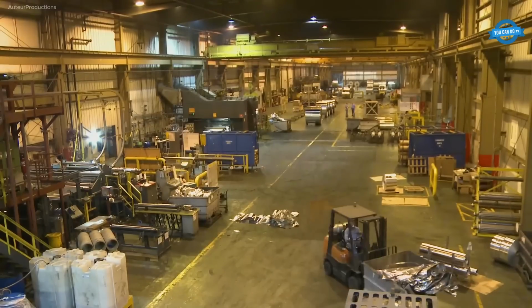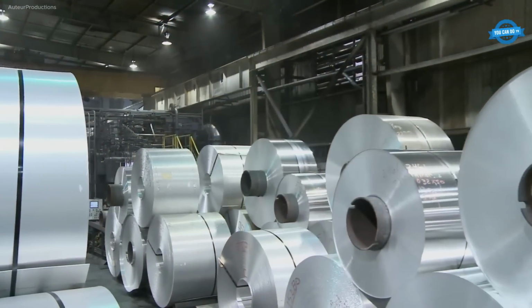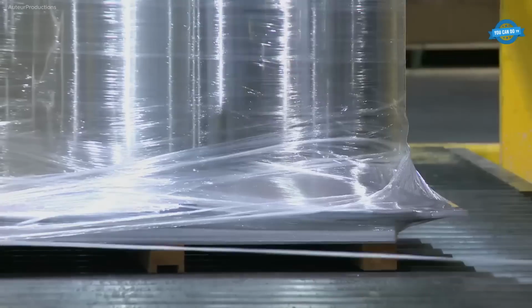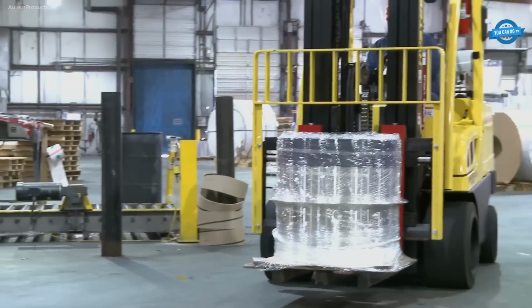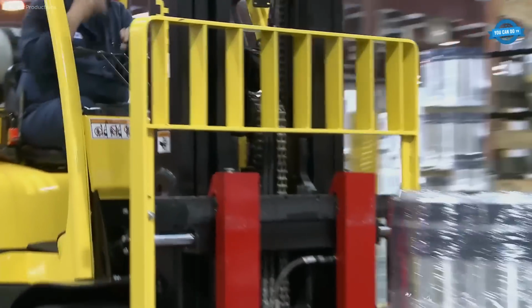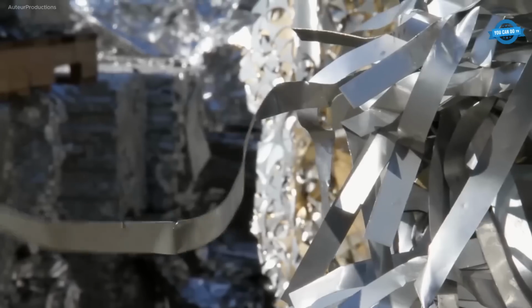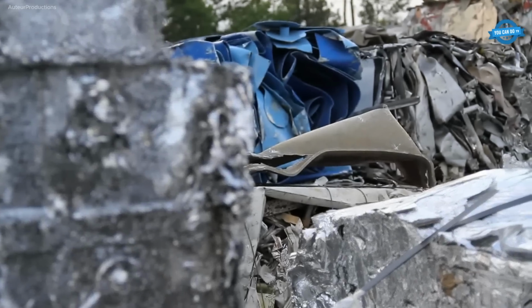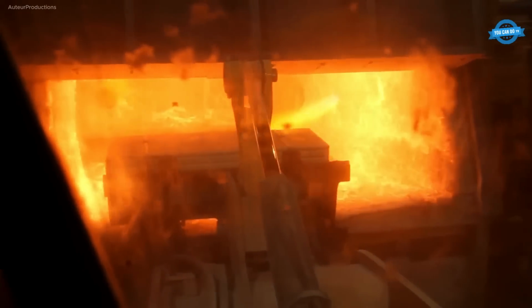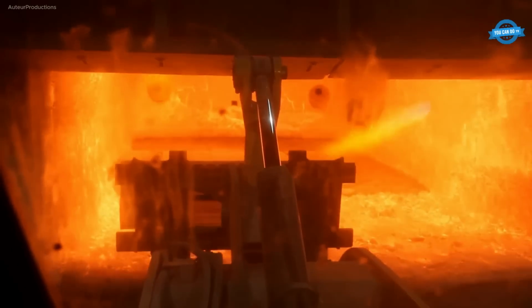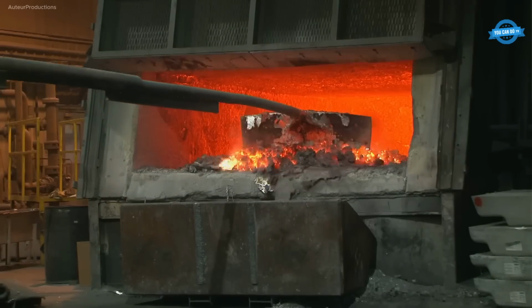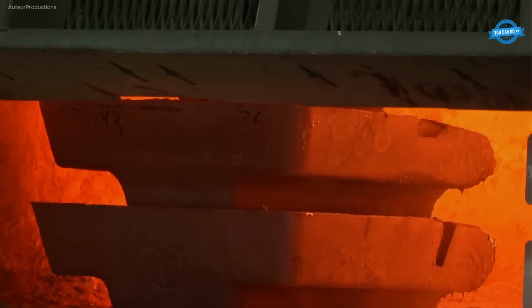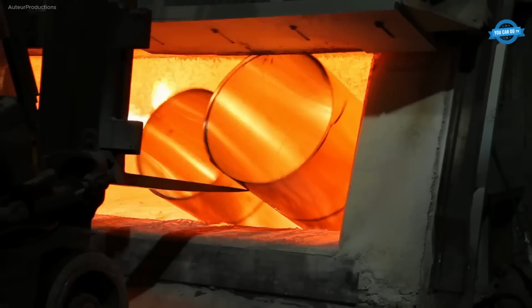At JW Aluminum, the aluminum rolling process is a continuous operation conducted 24/7 across 4 U.S. plants. It begins with blending prime aluminum ingots and recycled scrap to form the correct alloy. These materials are melted in large furnaces at over 1,000 degrees Celsius, where furnace operators maintain cleanliness, optimize metal recovery, and ensure the alloy meets required chemistry.